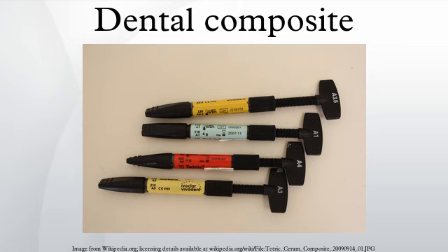Direct dental composites. Direct dental composites are placed by a dentist in a clinical setting. Polymerization is accomplished typically with a handheld curing light that emits specific wavelengths keyed to the initiator and catalyst packages involved. When using a curing light, the light should be held as close to the resin surface as possible. A shield should be placed between the light tip and the operator's eyes. Curing time should be increased for darker resin shades.